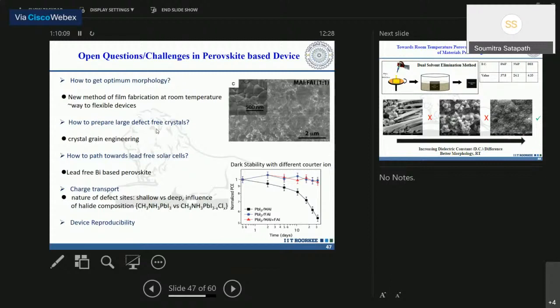If the formation energy of the trap is low, we call it a shallow defect state. If the formation energy of the defect state is high, we call it a deep defect state. Either way, the defect is a trap for the recombination of electrons and holes. If the electrons and holes get trapped in these defect states, I don't get much current from the circuit. So when growing the crystal, how can I do crystal grain engineering to grow a large, quality crystal with fewer grain boundaries and fewer defects?